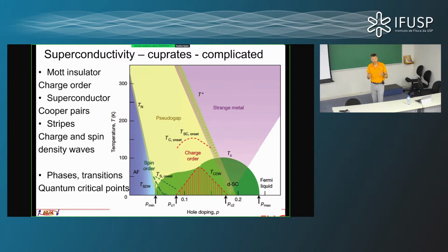So you would think naively, okay, fine, so now I will recover a simple metal. It turns out that's not at all the case, because in fact what happens is that you get a superconductor. These are the so-called high-temperature superconductors. You can have superconductivity all the way up to 150, 160 Kelvin. From 150 to 160, you have to ask Julio, because you need to apply approximately 5 GPa of pressure to get there, to get the world record.